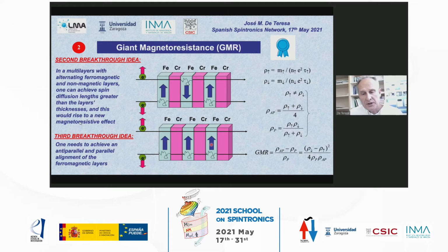When you have all the ferromagnetic layers aligned in a parallel way, then for the spin up channel, there is very little scattering. So the current is mostly shunted through the layers. However, the spin down electrons will suffer scattering in all the ferromagnetic layers. So you can calculate the resistivity in this parallel configuration and you get this result. So if you calculate the difference, you obtain the giant magnetoresistance.